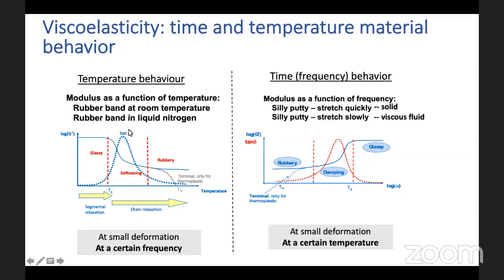If you take a rubber band at room temperature, the rubber band will be very elastic. You can extend it a lot. So the rubber band is in the rubbery region. But when you cool it down to liquid nitrogen temperature, then you cannot extend it. The rubber band is now brittle. It is a glassy solid, and it has a very high modulus, in the order of a few gigapascals.